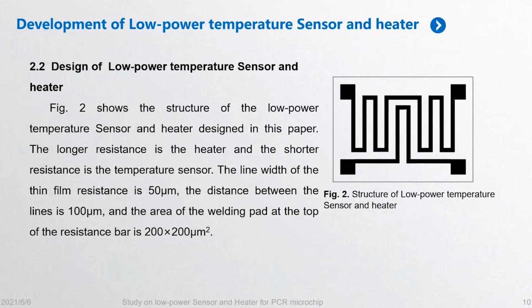Figure 2 shows the structure of the low-power temperature sensor and heater designed in this paper. The longer resistance is the heater and the shorter resistance is the temperature sensor. The line width of the thin film resistance is 50 micrometers, and the distance between the lines is 100 micrometers, and the area of the welding pad at the top of the resistance is 200 multiplied by 200 square microns.